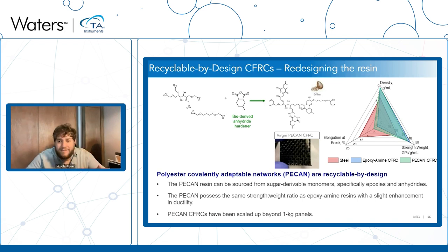And so what we have done at NREL is we've formulated this polyester covalently adaptable network that has material properties to rival epoxy-amine carbon fiber reinforced composites. So what you see here on the right, and what you'll see for the rest of my quick talk, is the typical thing we do at NREL, where we plot our data on a spider chart, where being on the outside of the spider chart is good, being on the inside is less desirable.